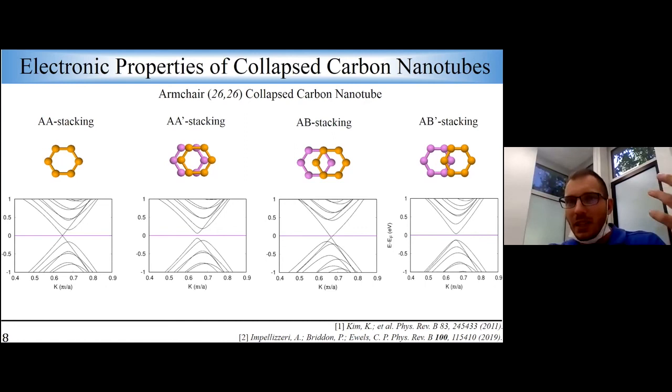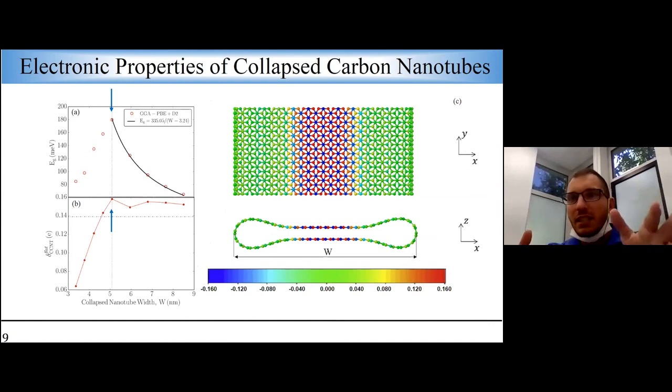At this point, we found an explanation in terms of the study of the charge distribution along the nanotube geometry by changing the corresponding sizes. And it is possible to observe, by overcoming a given threshold of the width, a charge difference distribution between the central flat region and the edge cavity, demonstrating in such a way a sort of intrinsic polarization of the nanotube, in an equivalent way to bilayer graphene after the application of the external electric field.